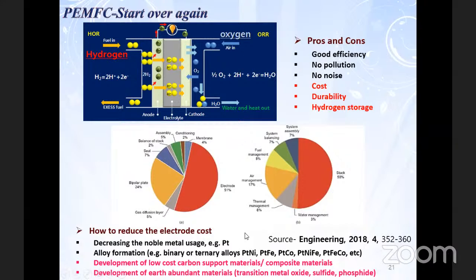Okay, how can we decrease the cost? By alloy formation. For example, platinum nickel, platinum Fe, platinum cobalt, and in this case, you can decrease the use of platinum to 50%. If you use ternary, quaternary, earth abundant material, you can decrease the cost even more. But somehow you have to sacrifice the efficiency, or these materials are not as active as compared to the platinum.